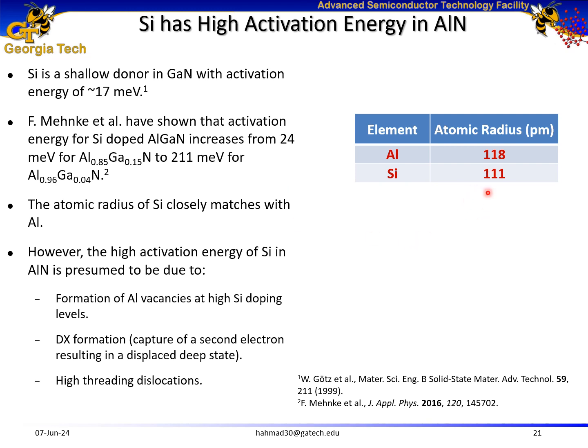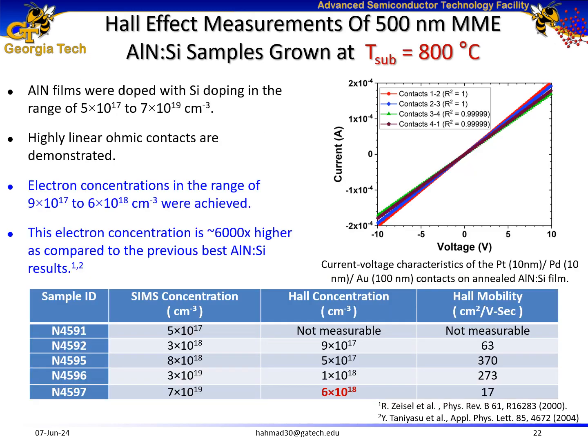So although the atomic radius of silicon closely matches with aluminum in aluminum nitride, due to several reasons, for example, formation of aluminum vacancies, DX formation, which is transition of silicon from shallow to deeper states, and threading dislocations, the activation energy of silicon in aluminum nitride is high.